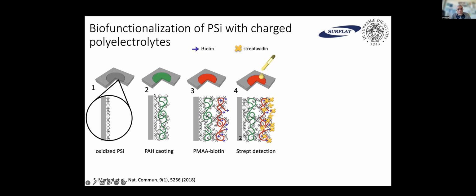In this case, for example, we took a porous silicon layer, and then instead of relying on the typical chemistry for silicon functionalization, we came out with this new approach, which is the layer-by-layer functionalization with polyelectrolytes. The advantage of this approach is that you can use the polyelectrolyte to perform a conformal coating of a very high aspect ratio structure. So we are able, with a single layer of polyelectrolyte, to completely coat all the pores of the porous silicon layer up to several micron depth.